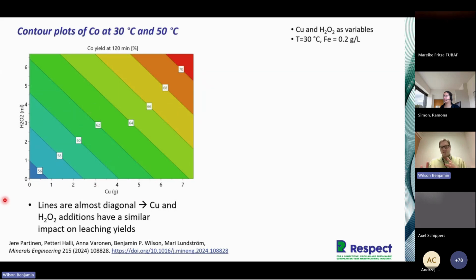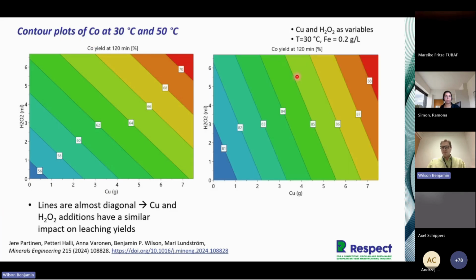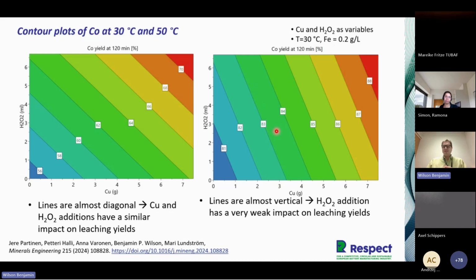So that would suggest, when comparing copper versus peroxide, that the copper and peroxide have similar impact on the leaching yields, at least after 2 hours at 30 degrees. Whereas if we look at 50 degrees, you start to see a change from the 45-degree angle towards more vertical. So this would mean that the peroxide addition, at this temperature, has only a weak impact on the leaching yields. So it's actually the copper addition that's having the most impact rather than the peroxide.